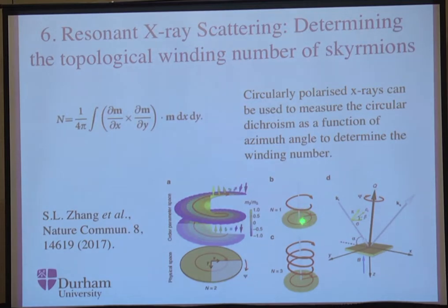These will be the equivalent diagrams for n equals 1, n equals 3. And the experiment is rather simple. You come in with an incident beam onto your sample here, scattering at a certain angle, and then you have an equal angle that's scattering off, so this would be the 2 theta angle. We apply a magnetic field that is normal to that surface. And we define an azimuthal angle around which we can rotate the sample.